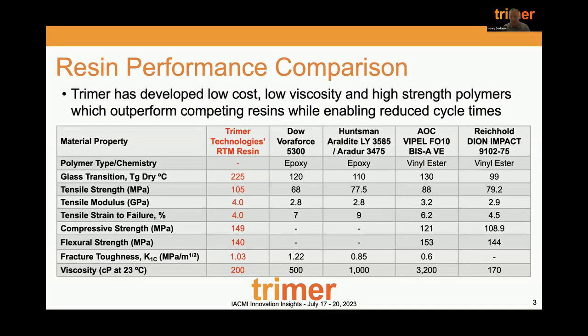Across the screen there are a number of two epoxies and two vinyl esters. One thing you might note is the vinyl ester viscosity is totally dependent on styrene content. Our resin is styrene free. So if you're thinking about future components where you may want to eliminate styrene and eliminate VOCs, our resin system is something that's going to enable that. So if you're using brominated vinyl esters, you can move away from those types of systems. The mechanical properties you see are quite significantly better than competing automotive resin systems.